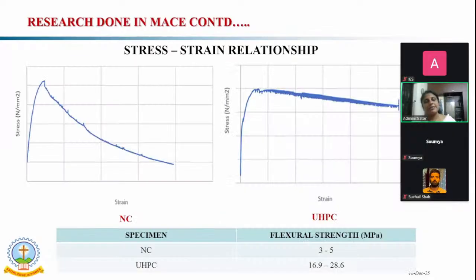Then when we consider the stress-strain relationship, or the flexural strength behavior, after the post-peak behavior, in the case of conventional concrete, there will be a sudden drop in normal concrete. But in the case of UHPC, due to the presence of fibers, after the post-peak point, there is no sudden drop. A controlled damage or controlled crack pattern will occur. This is the pattern in the stress-strain relationship or the flexural strength of the UHPC specimen. In the case of normal concrete, the flexural strength is 3 to 5 MPa, but in the case of UHPC, we got 16.9 to 28.6 MPa, from M120 concrete to M175 concrete.